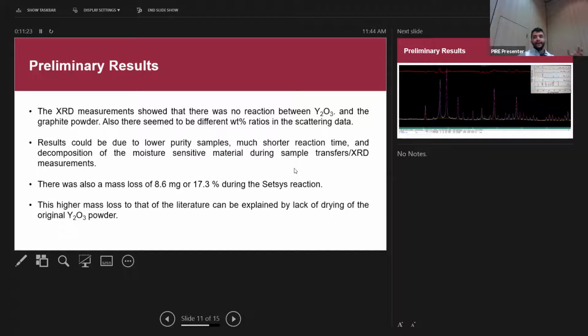Again, the lab right now sits pretty far from the XRD room, so I have to transfer it out. We offset the time it takes just by using a vacuum sealed container before I transfer it. There was also a mass loss of about 8.6 milligrams or 17% during the Setsys reaction, which is about double what we should be looking at.